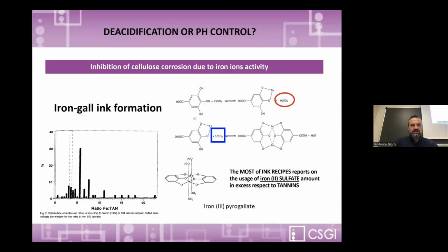And we focus this question working on the issue of inhibition of cellulose corrosion due to iron ions activity. All of you well know that iron gall ink is a really nice ink, really beautiful and very stable when prepared according to specific recipes. But you know that in the past, a lot of recipes foresaw a significantly higher amount of iron than necessary. The work by Jan Wouters, beginning of the 90s, was really important because working on more than 100 different recipes, you realize that most of them, the majority of them, go beyond the right ratio between the amount of iron salt and gall.